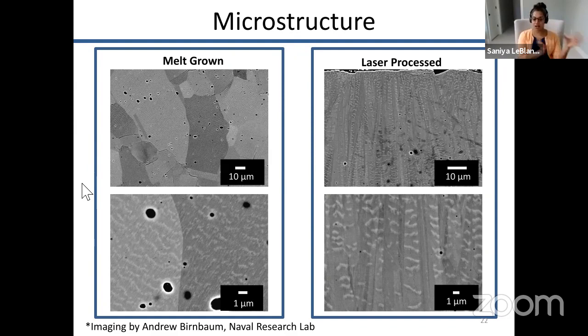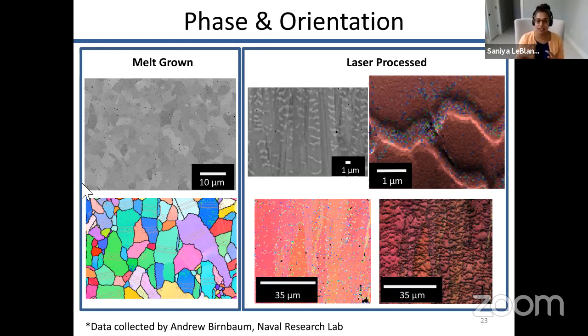So here we have a way where not only could we make a unique device structure that you can't make through the typical manufacturing techniques for thermoelectrics, but we could also control the structuring at the microscale. So that's really interesting. We also have looked at how the structuring impacts the phase, so the orientation of those unit cells in the material. And we see that with the laser processed material, you do get a preferred orientation. This processing gives us results that are very different from the traditionally processed material, and understanding how we can control the process and the resulting structure allows us to maybe tune the way the material would behave thermally, electrically, and mechanically.